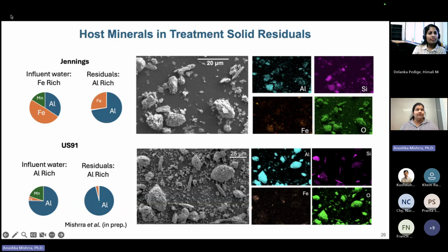The other limitation of using an SCM is that if you have very small amounts of REs, for example, in this case, the weight percent of REs is less than 1 weight percent, it cannot be captured easily using an SCM technology. But it is definitely a helpful technology to look at more abundantly present elements, like I said, iron, aluminum, and even silica that has shown up on our maps. So it's definitely a good screening process.